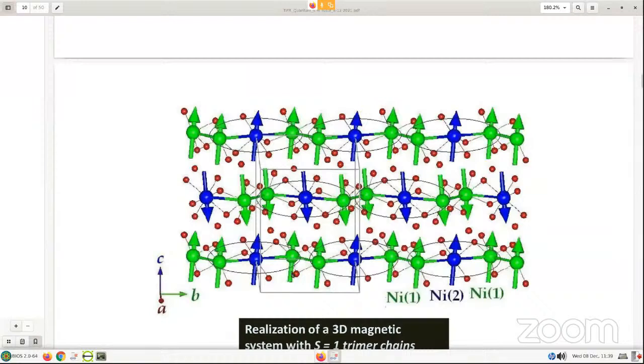Now we have also solved the magnetic structure, as you see here, how the magnetic moments of these 2 crystallographically inequivalent nickel sites, that is nickel 1 and nickel 2, are coupled. And as you see, this is 1 chain, this is the 2nd chain, and this is the 3rd chain, and in this ellipsoid what is shown here is 1 trimer involving J1 and J2 exchange interaction. So trimers are shown, and essentially the exchange interaction between two chains, we'll see from the inelastic neutron scattering experiment, is antiferromagnetic, but along the chain it is almost parallel, but not perfectly. There is a canting. So canted ferromagnetic along the chain. That means it is a positive exchange interaction, but not fully ferromagnetic.